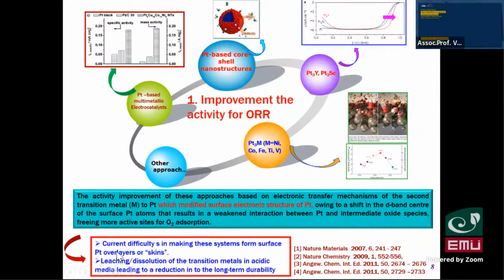However, they also have some disadvantages using this approach, because to make the platinum alloy with a second metal, they have a very complicated system. They make core-shell systems and multi-metallic structures, so making the bimetallic overlayer for this alloy makes the process very complicated, with a lot of steps to prepare this system.